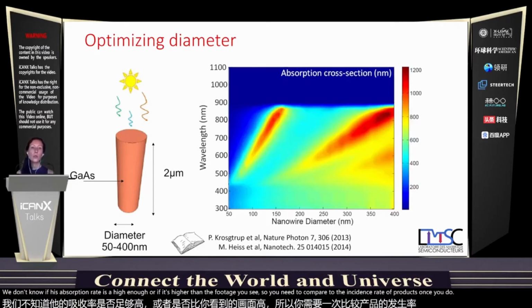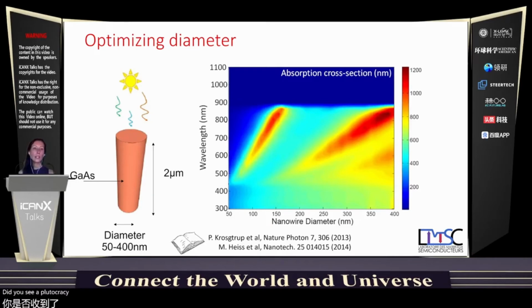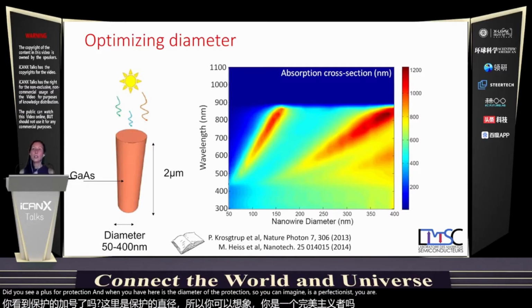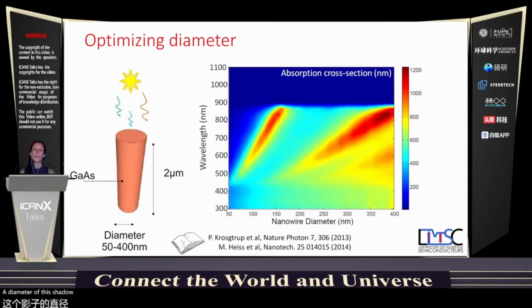Once you do this, you can deduce the absorption cross-section, and what you have here is the diameter of the cross-section. So you can imagine this cross-section as the diameter of this shadow area that develops in the nanowire, this area in which the photons disappear.